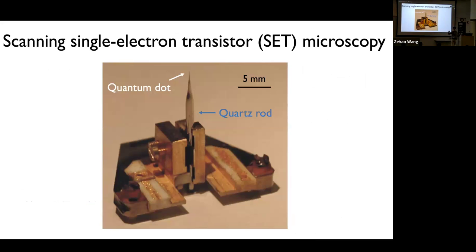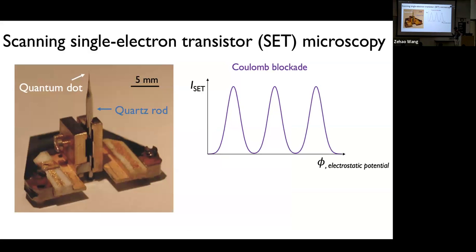I'll walk you through what this technique does, because this is a very special technique that only 3, actually 4, groups can do. The concept is you have this very sharp tip, and then using some procedure, we can fabricate a very, very small quantum dot right at the apex. The apex is around 50, 100 nanometers, so it's a nanoscale probe if you are being generous. The way we operate this probe is, if you try to monitor the transport characteristic across the quantum dot, what you will see is Coulomb blockade oscillation, because every time you can only allow one electron to tunnel in.